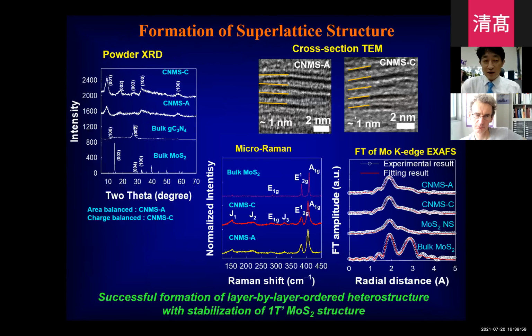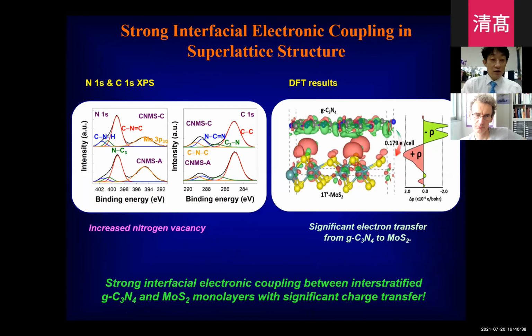We can confirm the layer-by-layer ordering of the monolayered MoS2 and monolayered carbon nitride from the XRD analysis and cross-sectional TEM analysis. From the Raman and the XAS analysis, we can confirm the transformation of MoS2 into 1T prime structures. As you know, the 1T prime MoS2 is very effective to enhance the electrical conductivity and electrocatalytic activity of MoS2 compared with the pristine 2H structures. Also, we proved the formation of defects from the nitrogen 1s XPS analysis. From that, we can confirm the increase of the nitrogen vacancy. So the hybridization can provide an effective tool to control the defect structure of the nanosheet.